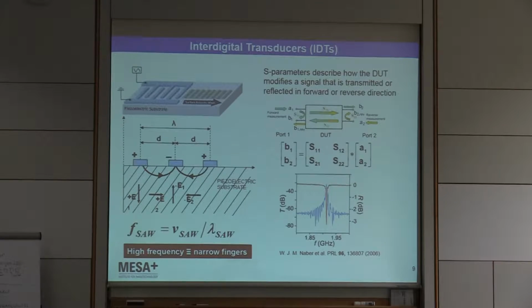The standard way of characterizing the performance of these IDTs is by fabricating two of these IDTs, with the same fabrication parameters, opposite to each other, and doing a so-called S-parameter analysis. So you look at a traveling surface acoustic wave from the sender to the receiver, and you see what the transmission is. You can also look directly at the reflection from a single IDT, so what power gets in and what gets reflected, and in this way you can determine all these S parameters, in particular the transmission and the reflection.